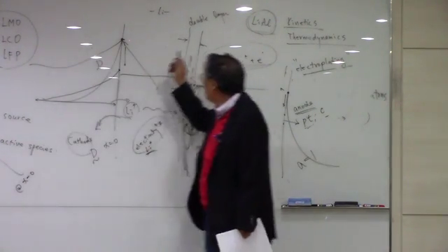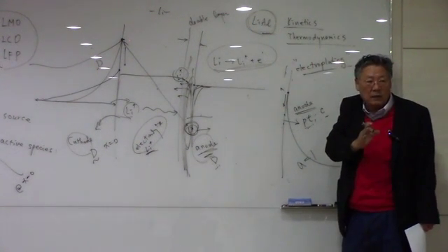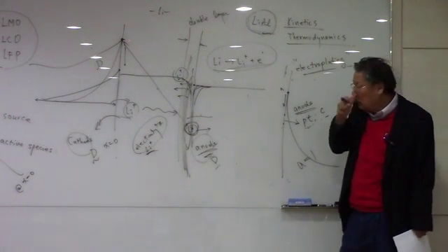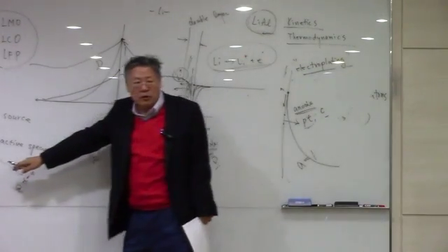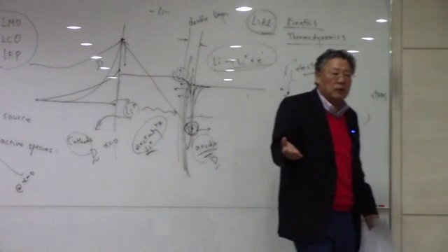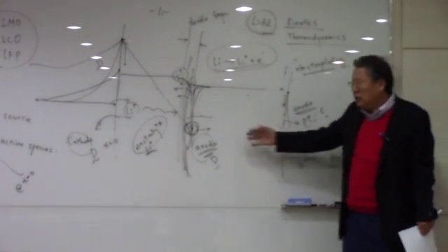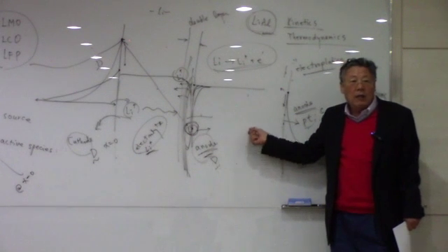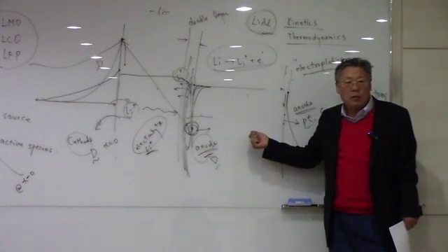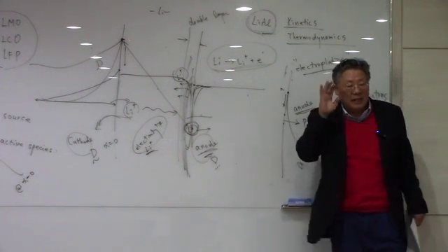In a compound, the activity of lithium is not 1. It's less than 1, okay? So it is going to sacrifice some of the voltages. For instance, if you have 3 volts as an open circuit voltage and you change the anode, then the open circuit voltage is not going to be 3 anymore. It's going to be less than 3.